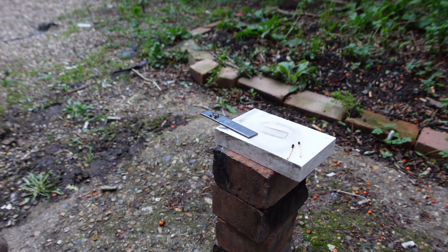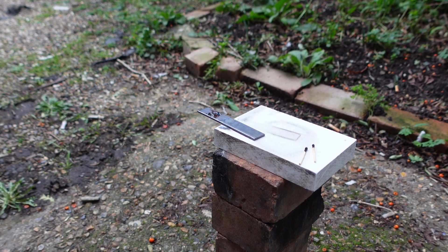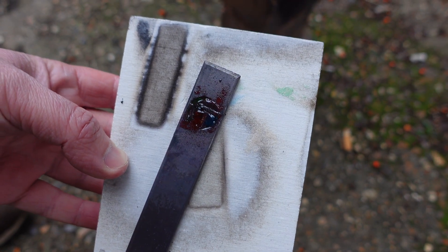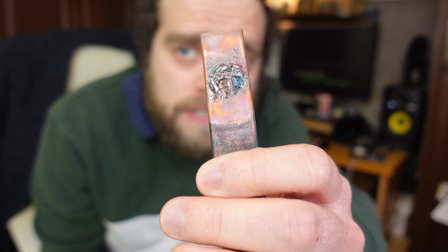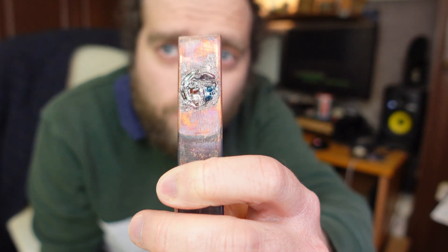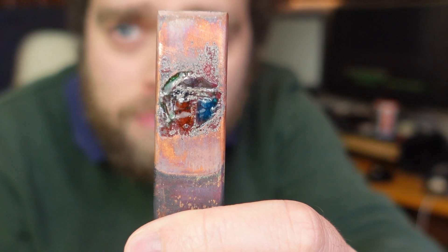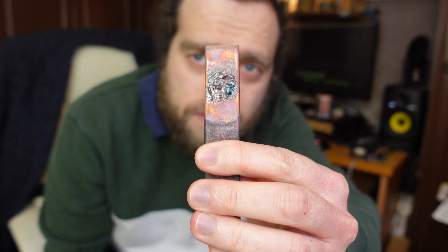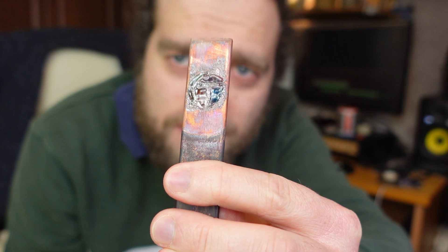The camera ran out of batteries but I think it's actually melted. Now all I've got to do is figure out how to get it back inside without burning myself. It's now a couple of days later and as you can see, while it's definitely more successful than my last attempt, it's still got some way to go before it can be considered to be working well as a process. I think I managed to get it hot enough that I also melted the silver underneath, because you can see silvery blotches underneath bits of the glass. The glass is definitely melted — that's definitely progress — but it's also very bobbly and lumpy, which is definitely not the look I was going for.